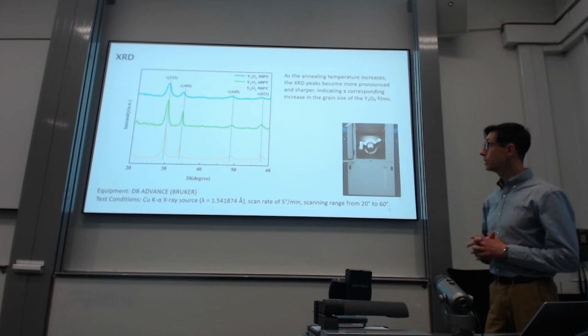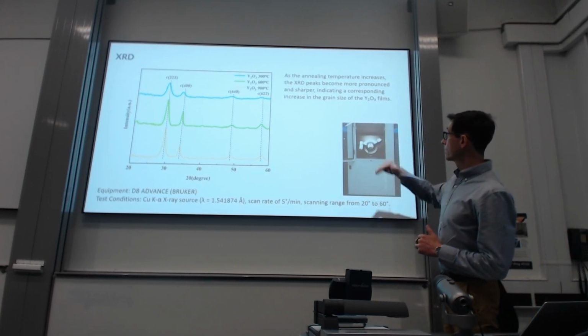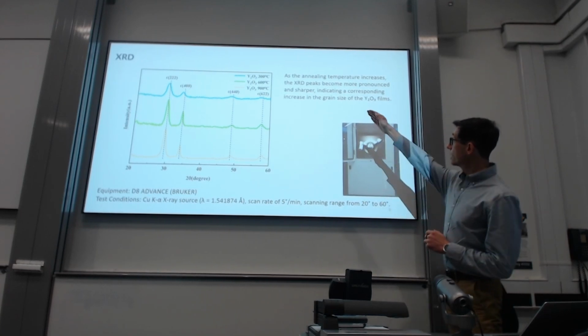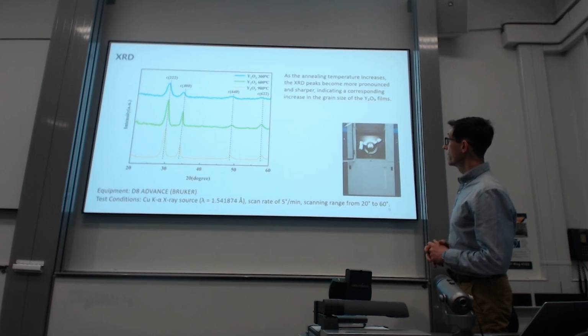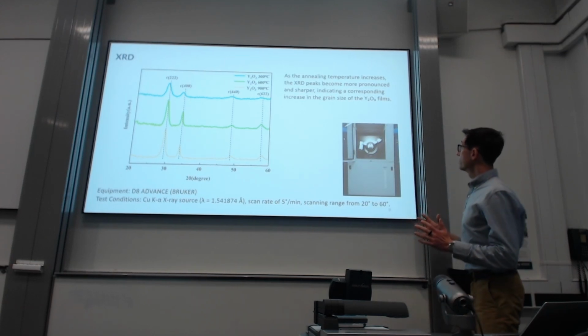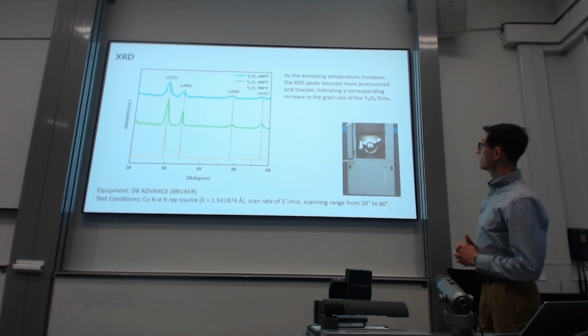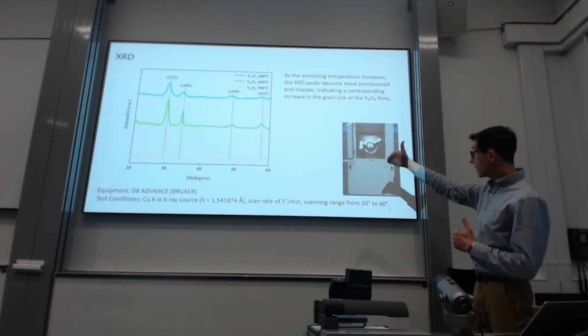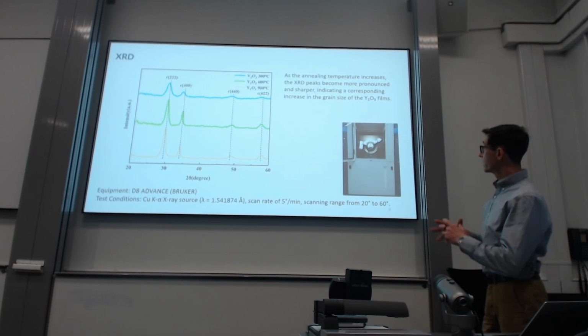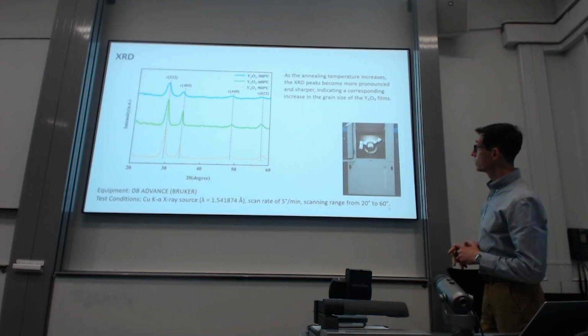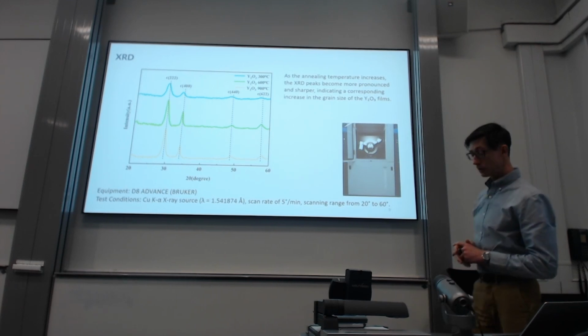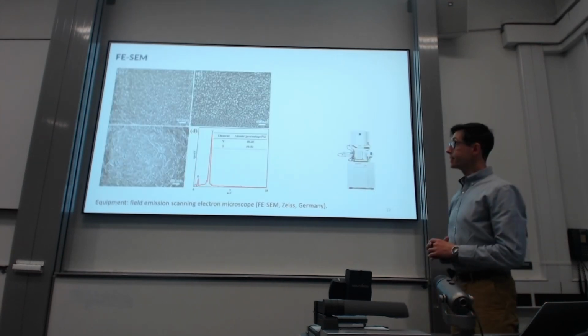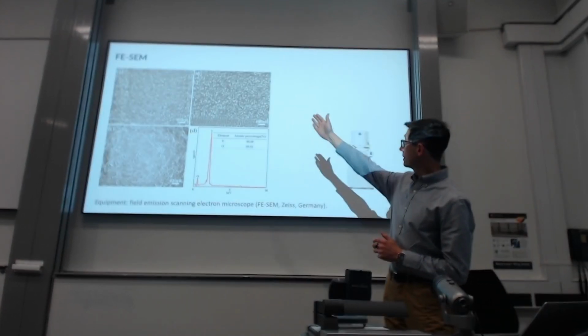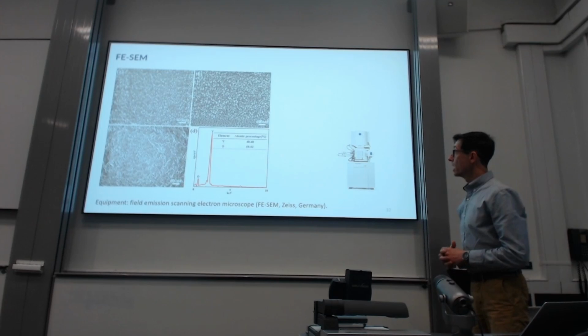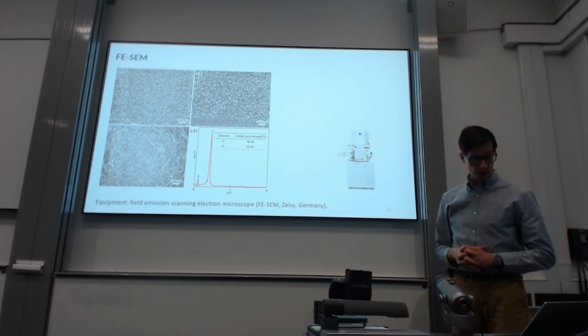Let me start with XRD results. So you can see 3 characterization outputs for the coatings, for 300 at the top, 600 in the middle, and 900 annealing temperatures there. So basically, with the outcome there, the increasing annealing temperature causes the XRD peaks to become more pronounced and sharper, indicating perhaps a corresponding increase in grain size of those coatings. And indeed, if you look at the SEM images of those coatings, again, 300, 600 and 900, you can clearly see some evolution of the grain size for the coating variants.